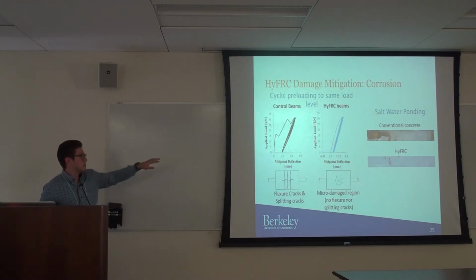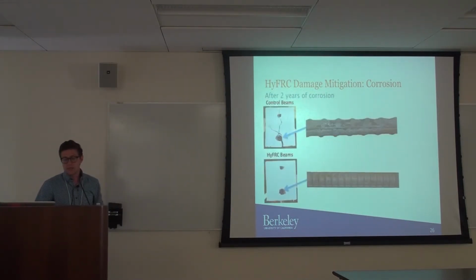So, conventional, this is just the surface characteristics. You see a big crack and a lot of corrosion products on the conventional, and in the HyFRC, very, very little. The state of these beams afterward: the conventional had a large splitting crack. You can see that the rebar itself on the top, maybe it's a little hard to see, had a lot of material missing from it, whereas in the HyFRC beam, it looked almost pristine.